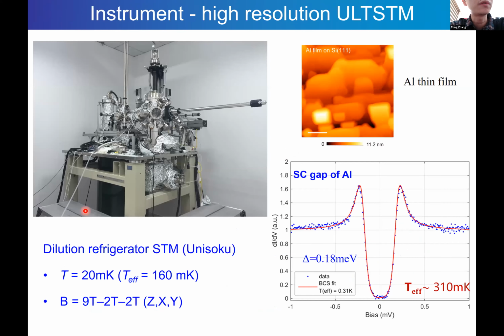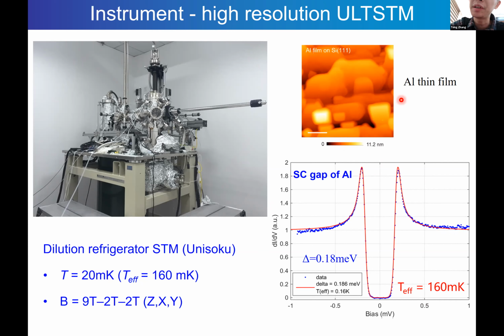So our study is performed in this dilution STM. It has a base temperature of 20 millikelvin. In this study, the effective temperature is about 300 millikelvin. It's calibrated on the aluminum film, and now the resolution is improved to about 160 millikelvin. So we can correctly resolve the U-shaped superconducting gap of the aluminum film.